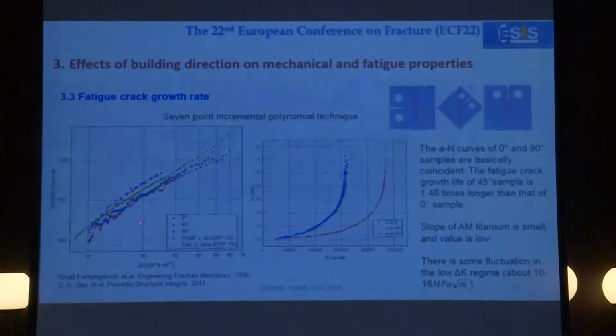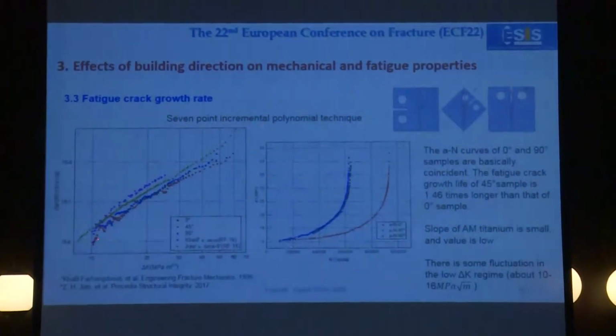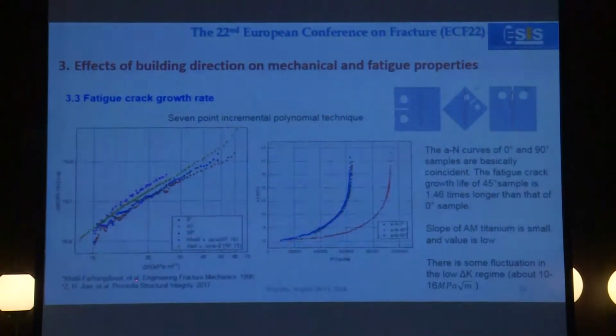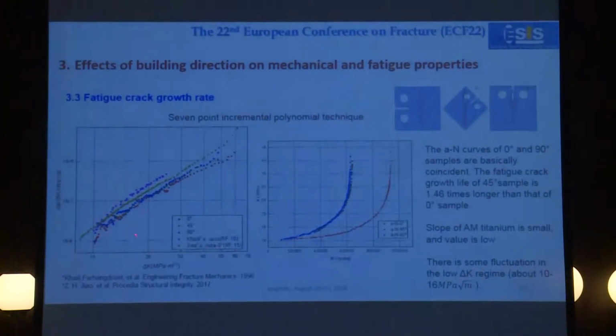And based on the 7-point incremental polynomial technique, the da/dN versus delta K curves were obtained in this picture, and we compared our test data with two references. One is also an AM titanium alloy, this green line, and one is the traditional titanium alloy. From these pictures, we can find that the slope of AM titanium alloys is smaller than the traditional ones, and the value of our test is lower than the others. And also in the low delta K regime, there are some fluctuations.